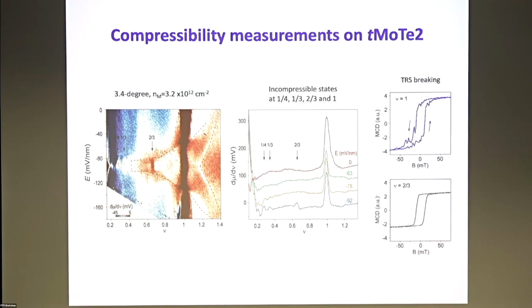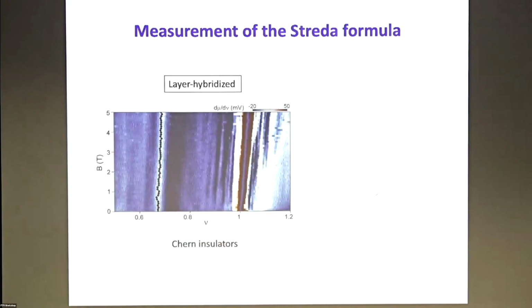And another measurement that we can do, because now we are doing it locally, optically, to read out the chemical potential, we can also do another measurement, which is the magnetic circular dichroism, to see whether there is time reversal symmetry breaking at the same point on the device. For instance, if we park at filling factor 1 here at small electric field, you see a nice magnetic hysteresis curve that shows that the system really breaks time reversal spontaneously. And if you park at 2/3 at this state here, you also see the nice magnetic hysteresis. So the states are certainly incompressible and they are also magnetic. And so the question is whether these states are Chern insulators or not. To do that, we try to measure the Streda formula.